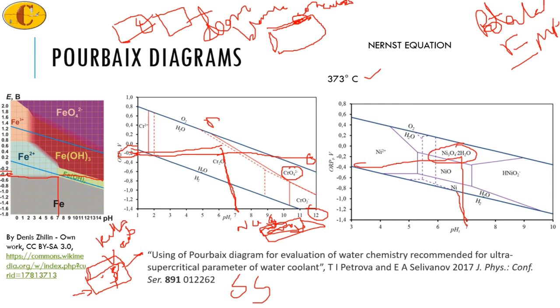However, if you go for a high pH, this NiO will react with the hydroxides to give HNiO2- at this temperature. And if we change the temperature, the region or the expanse of this area will change accordingly. As a result, the nickel oxide film will remain intact up to a certain temperature, but above that temperature also it will undergo a reaction and it will be lost. So the same mechanism will be seen as in stainless steel, with the underneath nickel undergoing reactions and hence corrosion. Now this is how the electrochemistry is actually related to what happens in caustic environments, and what has actually led to the formation of the caustic service charts.